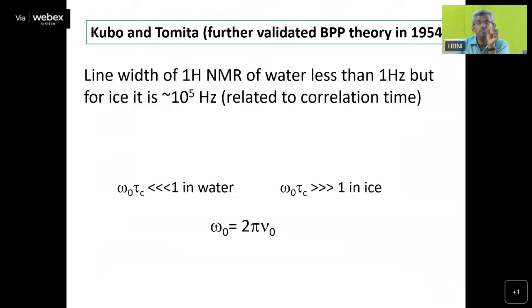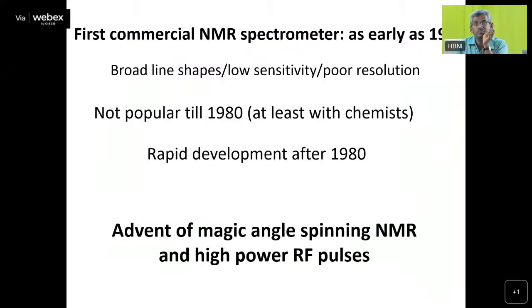Correlation time is nothing but the time between the magnetic field fluctuations. If you multiply the correlation time with omega 0, which is the operating frequency, you will get a number. If it is very much less than 1, you will get a very narrow line shape, and if it is very much greater than 1, you will get a broad line shape. Probably I will discuss this aspect when I discuss the relaxation time.